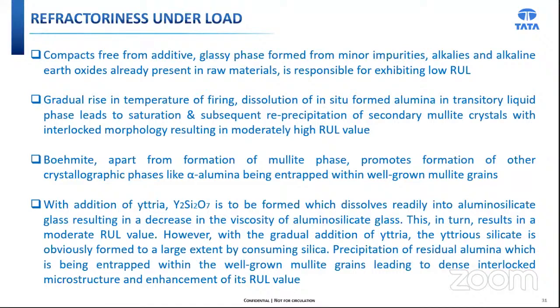In the presence of yttria, yttrium silicate is formed, which dissolves readily into the aluminosilicate glasses, resulting in a decrease in the viscosity of the aluminosilicate glass. This in turn results in a moderate RUL value. However, with the gradual addition of yttria up to 1.5%, the yttrium silicate is obviously formed to a large extent by consumption of silica. The yttrium silicate in turn leads to precipitation of residual alumina, which is entrapped within the well-grown mullite grains, leading to a dense interlocked microstructure and enhancement of its RUL value to 1675 degrees centigrade for the sample fired at 1575.